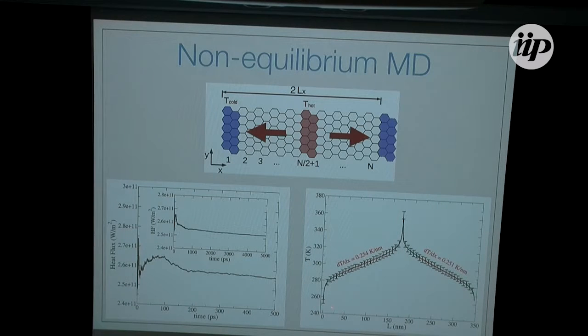And I can calculate the temperature at each part of the system. I divide the system into imaginary boxes, let's say. In each box, I have a certain number of atoms. I take the average kinetic energy of those atoms. That's the temperature in that area of the system. If I do that for the whole system, I have low temperature here, high at the center, low again, and when the system reaches its steady state, the temperature gradient can be calculated just from this slope here, and it must be very close on both sides. It's just the average kinetic energy. I'm not sure if I should call it temperature, but it's the average kinetic energy in that region of the system, and you clearly see that it does vary as we expected.